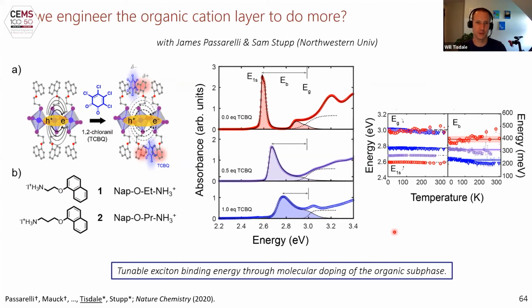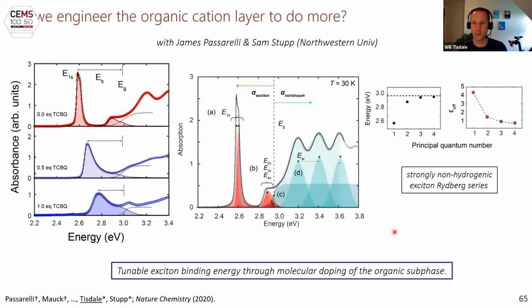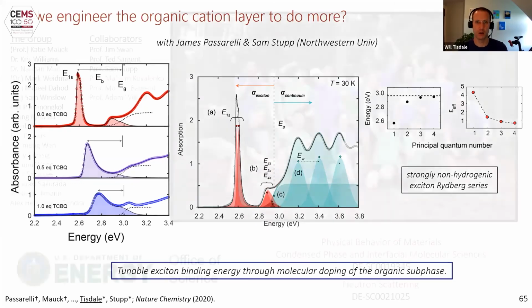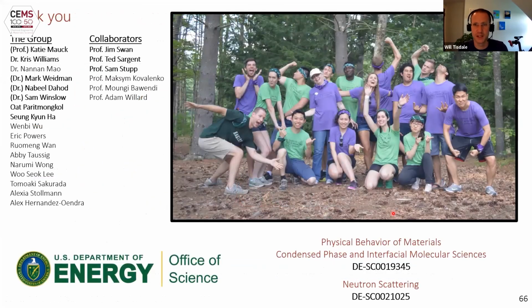And so by putting different amounts of this molecular dopant into the organic layer, you can take this very strong exciton binding energy and make it weaker. Along the way, we learned a lot about the hydrogenic or highly non-hydrogenic exciton Rydberg series in the absorption spectra. This has been the subject of some debate, whether this is the onset of the band edge absorption or actually the contributions of higher Rydberg states of the excitons. Okay, with that, I will stop and take some questions.